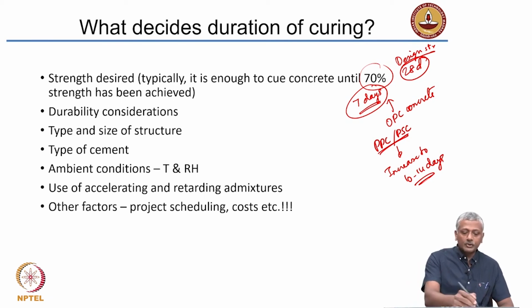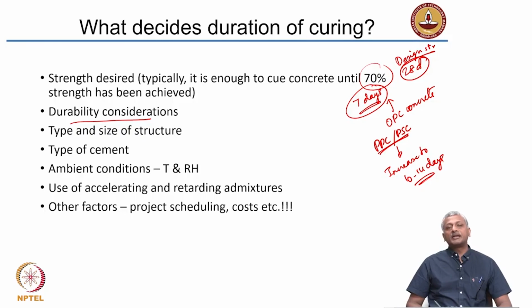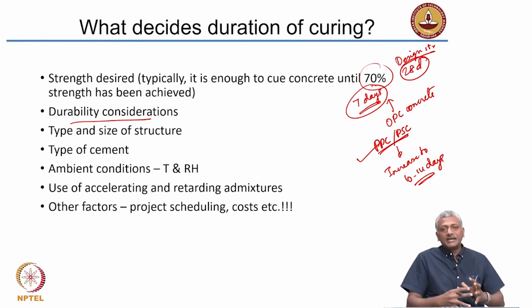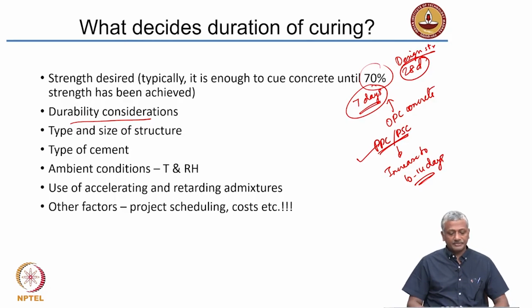Okay. Curing also needs to be based on durability considerations. In some situations, if you have to protect the structure for a much longer period of time, you need to be prepared to cure for that period of time. Okay. The type and size of the structure, the type of cement, as I said, the ambient conditions, temperature and relative humidity will also determine the degree of curing to be provided. For instance, if you are in an environment where the external temperatures are very low, then the concrete strength gain is going to be severely restricted. As I said again, in such cases, use of insulating blankets is a good way to keep the heat inside so that the concrete gains strength much faster.